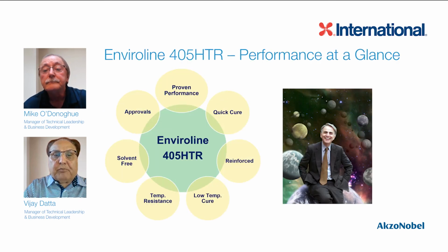So let's see the performance of 405 HTR at a glance. Number one, it has a proven performance. It has a long history of proven performance in various tanks and oil processing facilities. It has a very quick cure, so you can put the tank into service very quickly. It is reinforced, so it can be applied at very high dry film thickness, which can comply with API 652. And it has a low temperature cure. A lot of coatings don't cure below 50 degrees or are not recommended. This coating can even cure at 40 degrees Fahrenheit.